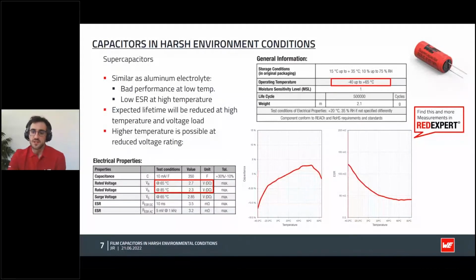Finally, supercapacitors of the electric double layer technology have similar temperature curves. The ESR also lowers at high temperature, increasing performance. Sadly, supercapacitors have a very limited temperature range because the combination of full rated voltage and high temperature will lead to a very short expected lifetime.